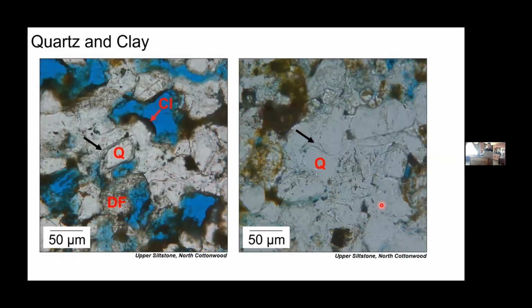Okay, so starting off with quartz and clay, and again, these are relatively minor phases compared to the carbonate cements we'll talk about next. But on the left here is a photomicrograph of a detrital quartz grain, where you can see a really easy to recognize syntaxial quartz overgrowth highlighted by this black arrow. And I'll also point out the proximity to a dissolved feldspar grain, you can see on the bottom of the photomicrograph here, and also the abundance of this brown material, which is illite lining on these pores.